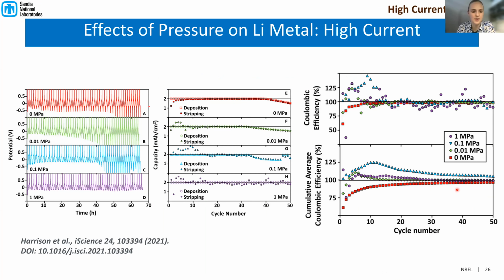And you can see this too in the electrochemistry. So going from 0 up to 1 megapascal, the electrochemistry got a little bit better, but there's still a lot of variability and a lot of scattering. You can see in the Coulombic efficiency that sometimes we were measuring over 100% Coulombic efficiency. And that's because we believe things can break and reconnect, and also that there are electronic shorts forming through the separator in the material. And we'll talk about that in a minute here.